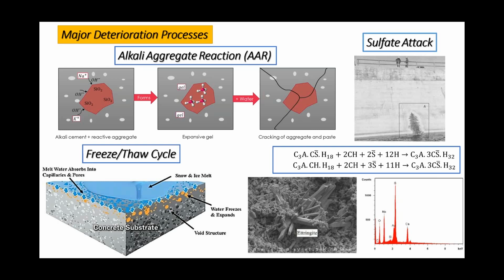But this phenomenon occurs due to the presence of calcium hydroxide in the hydrated Portland cement paste. When the cement paste comes in contact with sulfate ions, the alumina-containing hydrates are converted to the high sulfate form, which, as you can see in the photo, is going to form ettringite, which is not a good item for concrete, because eventually the growth of this crystal is going to induce pressure on the concrete surface, and these are also not stable crystals, so they may disappear, which is a special case of internal sulfate attack.